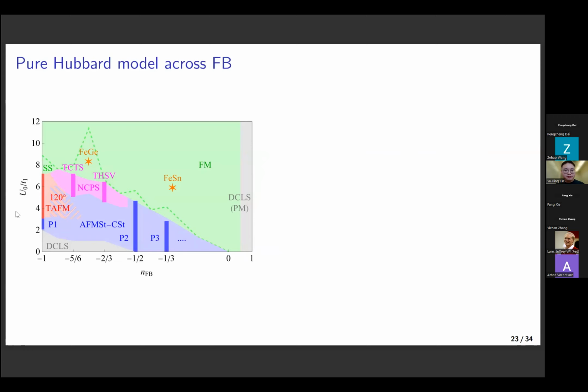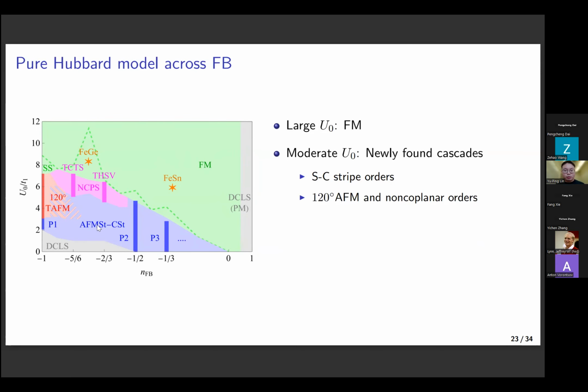So here is a brief summary of our discovery in a pure Hubbard model. If we look at the large U regime, we're seeing the ferromagnetism. And if we look at the moderate U regime, we're finding many new states. First, we will have the cascades of the spin and charge stripe. And second, we will find the evolution from the 120-degree coplanar order to the non-coplanar spin orders. And I want to briefly mention that if we look at the boundary of the ferromagnetism, we will actually find the spiral spin orders. And if we look at the very small U regime, we will find the ground state to have the dilute compact localized state. So this is a very brief summary of what we found in the pure Hubbard model across the flatband.